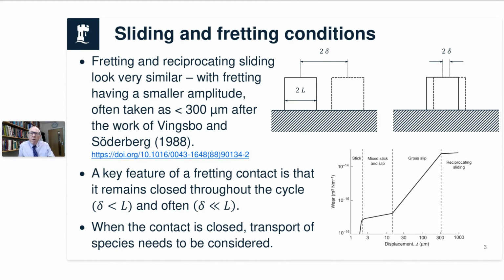But I would suggest that a key feature of a fretting contact is that it remains closed during the cycle. By closed, I mean that one or other of the members remains entirely covered by part of the original contact. It doesn't get open to the atmosphere. And when we talk about open to the atmosphere, we mean direct oxide contact with that surface, but it's probably also something to do with the way in which the debris is flushed out of the contact. So that's the idea of a closed contact. Of the two images at the top right of my slide, the right-hand one remains a closed contact, whereas the one on the left, where delta is larger than L, the contact width, is what we might refer to as an open contact. And in fretting, I would suggest there's always some level of closed contact.